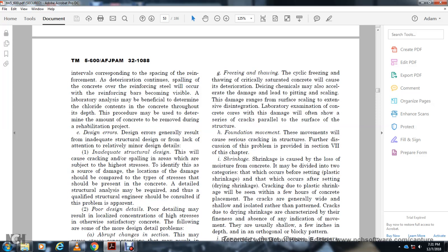Freezing and thawing. The cycle of freezing and thawing of critically saturated concrete will cause deterioration. Deicing chemicals may also accelerate the damage. Depending on the severity, the damage ranges from surface scaling to extensive disintegration. Laboratory examination of a concrete core of the damage will often show a series of cracks parallel to the surface of the structure.